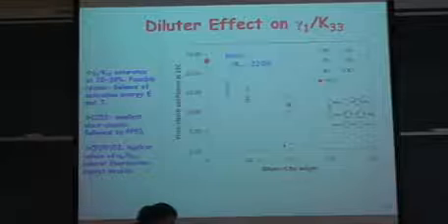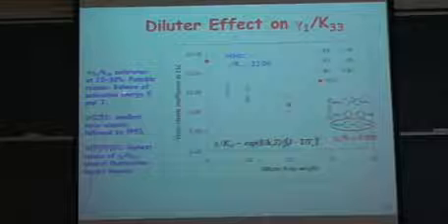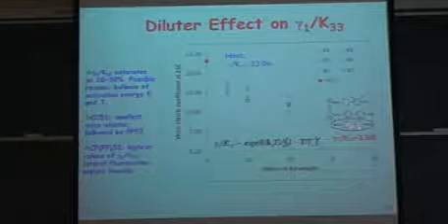This one is the diluter effect on viscoelastic constant. So we also compare again. Please pay attention to the trend. We found that the viscoelastic constant drops, but tends to saturate at some concentration. And another thing is that this one is the best. It has the lowest viscoelastic constant.